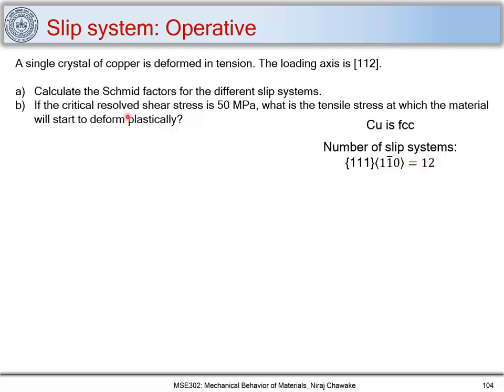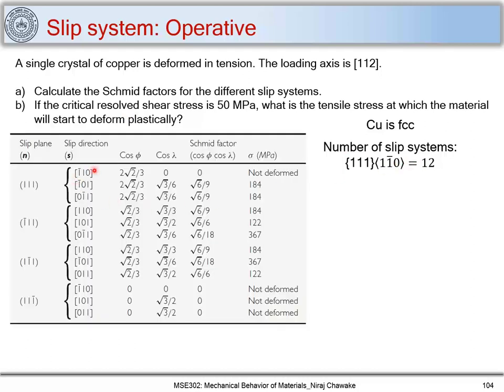We need to find which slip system is operative — it will be the one with the highest Schmid factor. Let's calculate all 12 slip systems. For slip plane (111) with slip direction [1̄10]: the loading axis is [112], giving cos(phi) = 2√2/3 and cos(lambda) = 0, so the Schmid factor = 0. There is no shear stress, so slip will not occur on this system.